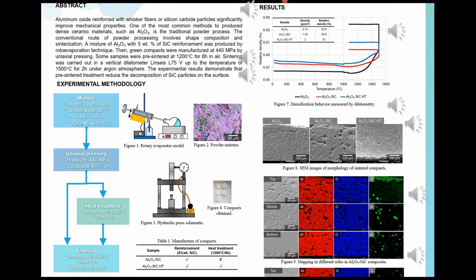Results. Through the sintering curves obtained in the dilatometer, the densification of the material during heating was analyzed. Figure 7 shows a comparison curve between the composites with heat treatment and those without pre-sintering. The results reveal that the relative density obtained in sintered compounds only reaches 51% in sample aluminum oxide silicon carbide HT, because silicon carbide is susceptible to oxidation under the atmosphere of inert gas.